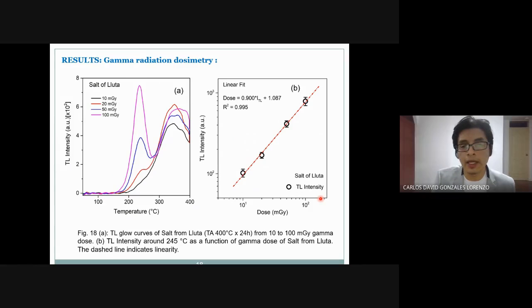Okay, now in order to know the dose response of this interesting TL peak, we did these measurements. First, this picture shows the TL glow curves of salt of Lluta, also with a previous thermal treatment of 400 degrees for 24 hours, after irradiation from 10 to 100 milligray gamma dose. The TL intensity around 245 degrees Celsius, as a function of gamma dose, is shown in this picture. Okay, we have a linear behavior, and the equation of this linear fit is shown in this part.